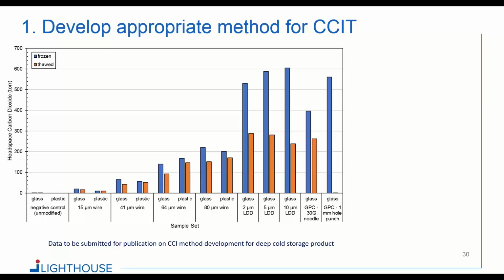And here, what we're plotting, again, it's a CCI test method based on detection of carbon dioxide. And so you see that all of these positive controls were detected with elevated carbon dioxide levels, meaning that they were leaking and that the test method picked them up. We were also looking at both glass and plastic vials here. You see those labeled there. And we were looking at, can you detect a leak in frozen products, so immediately after removing from deep cold storage? So that's the blue bars there. Or can you also detect these defects once the product has thawed and is at room temperature? And you see that in all those cases, you detect the defects as well.